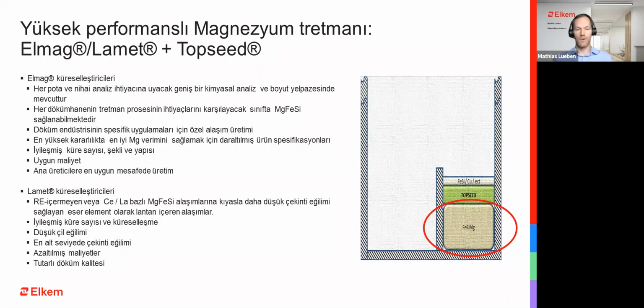Second, the Lamet nodularizer. The use of lanthanum as a source of rare earth in the alloy gives minimal shrinkage when compared to rare earth-free or cerium lanthanum-based magnesium ferrosilicon additions. It will increase the nodule count and nodularity with low chill tendency and minimize shrinkage. Lamet will ensure consistent casting quality with reduced costs. And as additional information, production of these alloys is close to major casting clusters.